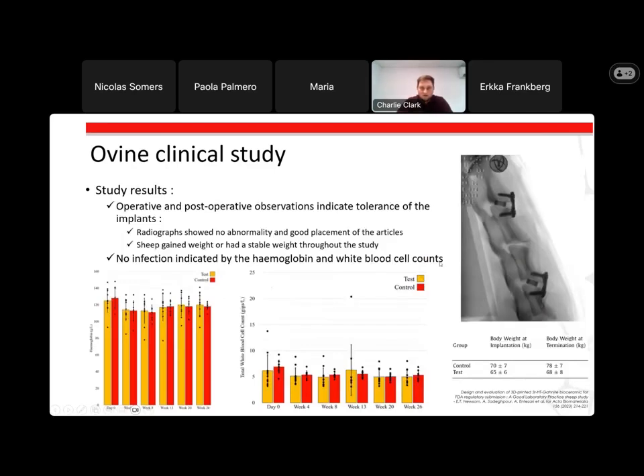What the study showed was that the implants were very well tolerated by the sheep's body. So we can see on the radiographs there's no abnormality. We can see that the articles are very well placed. You can see here where the screws and the metallic fixture is, and you can see where the spinal cages are in between the vertebrae. Throughout the study, the sheep gained weight or had a stable weight, which meant that the surgery did not cause them any harm or make them ill at all.